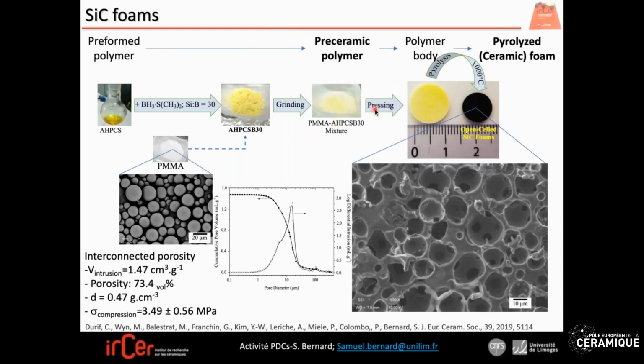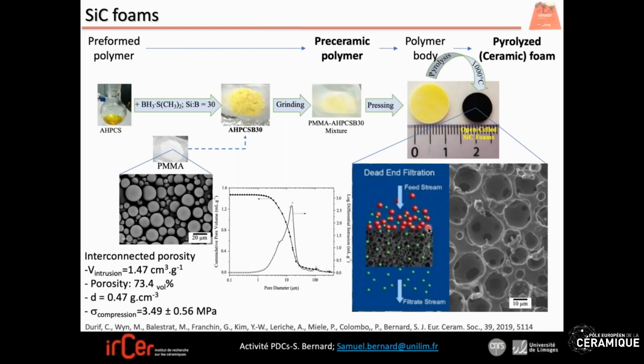That you press, this is a shaping process to form pieces, as you can see here, the yellow one, and you have a pyrolysis to transform your polymer into a ceramic. Why? The PMMA spheres disappear during the pyrolysis because they are decomposed, so they leave voids, and the voids are the pores of your materials. So the diameter of the pores depends on the diameter of the PMMA spheres. Here we use PMMA spheres with 25 microns in diameter, and you can see that we have an interconnected porosity. So it is clear that these materials can be used in dead-end filtration as a membrane.